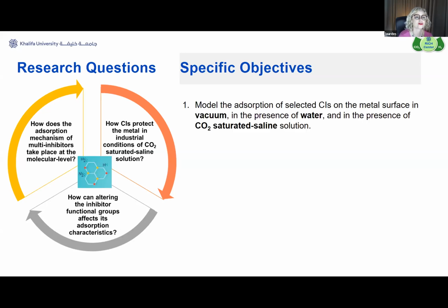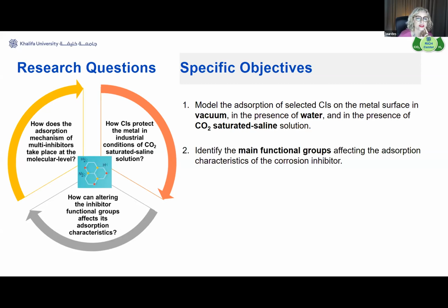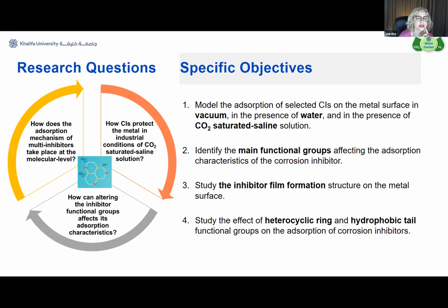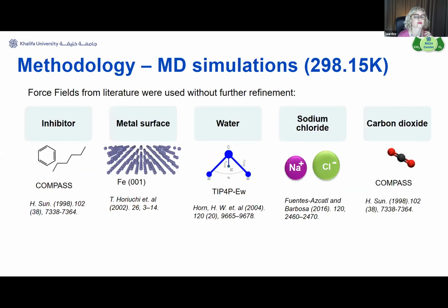protect the surface. So with this, the specific objectives of the work I'm presenting here today are to model the adsorption of these selected corrosion inhibitors on the metal surface in vacuum, in water, and when we also have CO2 in a saturated saline solution; to identify the main functional groups affecting the adsorption characteristics of the corrosion inhibitor; to study the inhibitor film formation, or the aggregation of them; and the effect of the heterocyclic rings and hydrophobic tails on the adsorption of these corrosion inhibitors. For this, we have used classical molecular dynamics simulations,